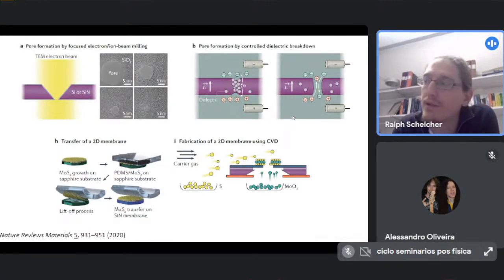One of them, as you can see here on the upper left part of the slide, is to actually use the same tool that I've shown you before to visualize them, and that's a transmission electron microscope. The electron beam, if it has a high enough energy, if the electrons are moving fast enough, they can knock out the atoms in a thin membrane, and they can actually create a hole, they can drill a hole. And you can use the TEM both to make the hole, and you can also monitor what it looks like. So that is one approach to do.